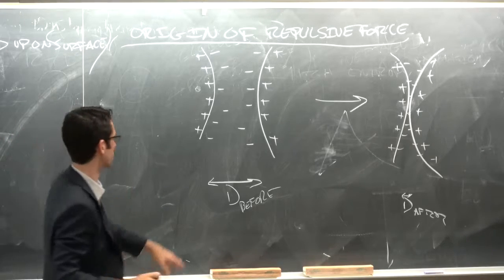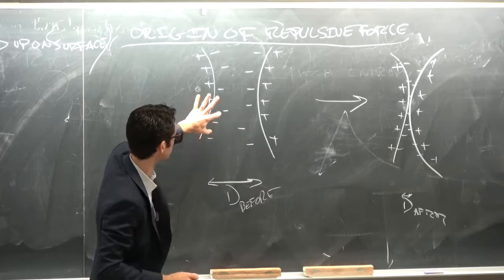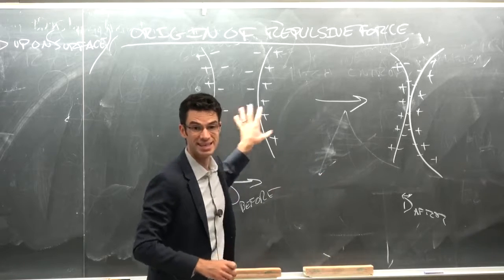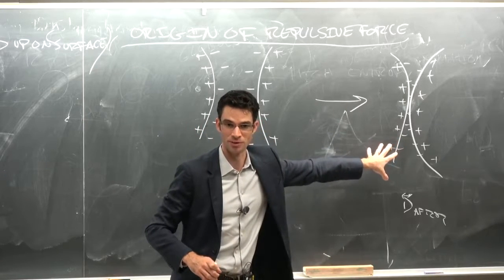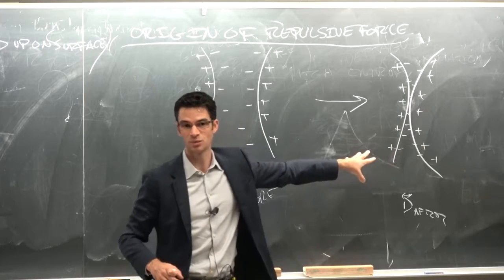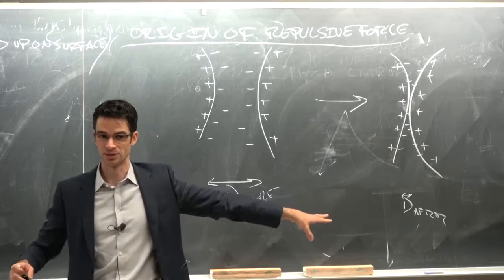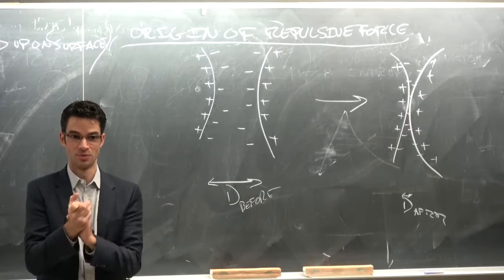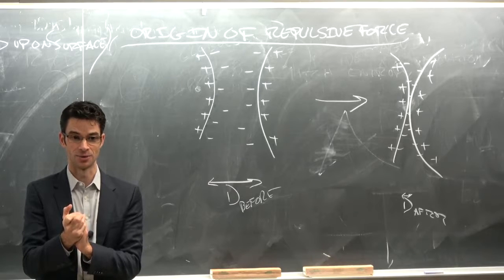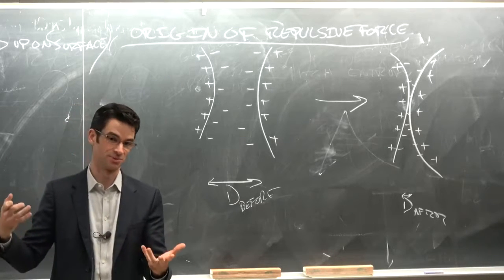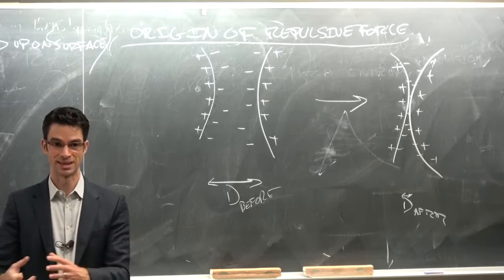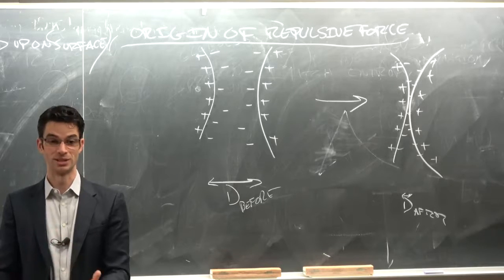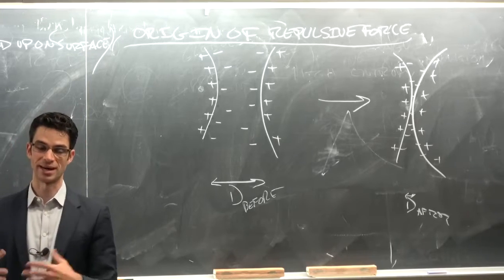And if you confine them more in the D before case, if these are even closer, then there's less of a difference between the energy in this case and the energy in this case, and therefore the repulsive force is less. And that's actually why if you take some nanoparticle solution and literally take the salt shaker and dump salt in it, the particles will coagulate or aggregate. Coagulate is really irreversible. Aggregate or flocculate is reversible generally. That's one strategy for precipitating particles out of a solution.